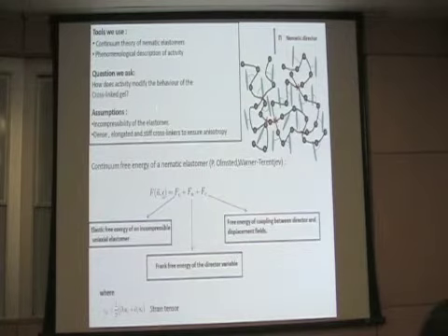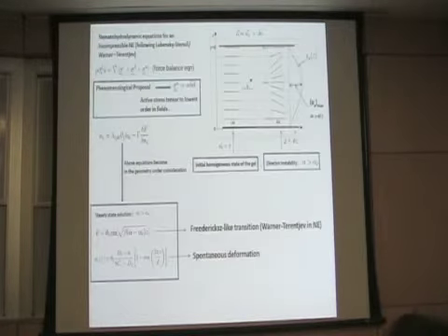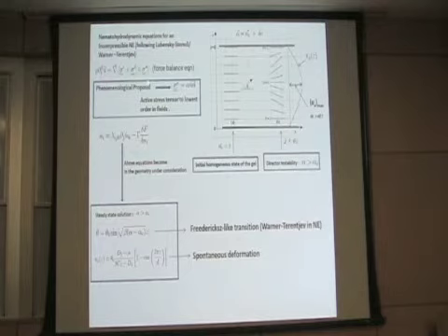We study it in a particular geometry, and we also assume that they are dense, elongated, and stiff crosslinkers so that anisotropy develops in the network. Now one can write down the hydrodynamic equations, and we phenomenologically add this active term to the stress tensor. Now this term can be justified by a more microscopic calculation.